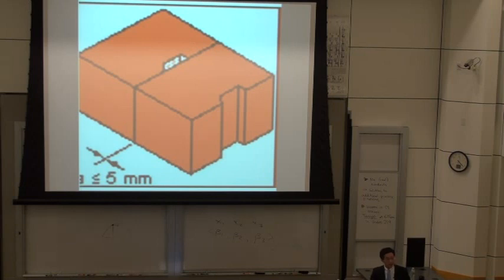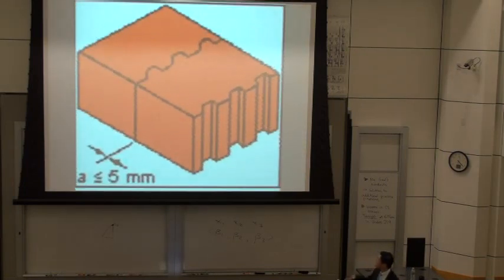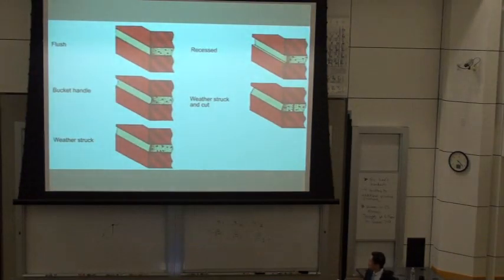That means you just fill a little bit of the head joint, or, in the modern way, tongue and groove. So tongue and groove is no mortar at all. This is due to the higher thermal insulation. From the bed joint point of view, as you probably know, for the normal bed joint we have different mortars. Either we use the normal calcium cement mortar, M5, where 5 means 5 megapascal in strength, or you have the thermal insulation mortar. So you have M5, M10, M15, up to M25 in megapascal. This gives the compressive strength of the bed joints, or as I said, thermal insulation mortar.